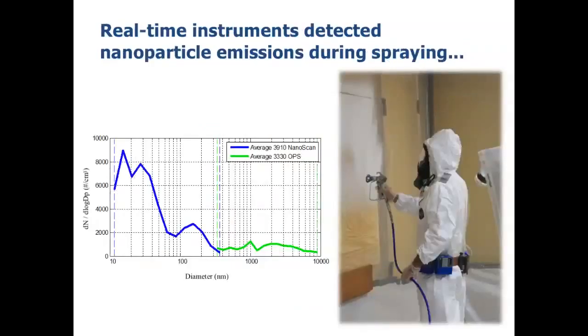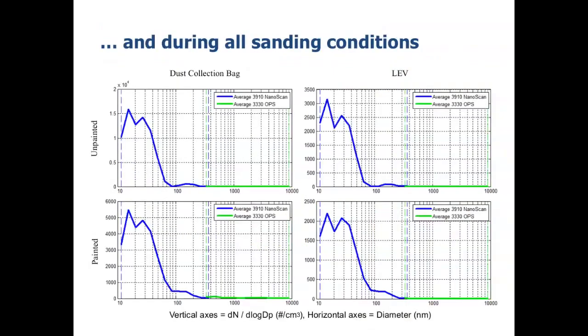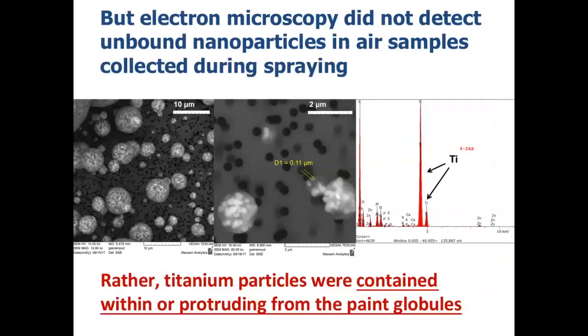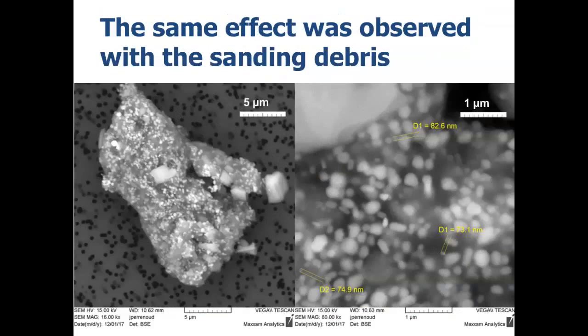And during the spraying, the real-time instruments detected nanoparticle emissions. The same was true during all sanding conditions, as you can see from the blue lines below the 100 nanometer cutoff. However, the electron microscopy did not detect unbound nanoparticles in the air samples we collected during spraying. So rather, what we observed, and as you see on this slide, titanium particles were contained within or protruding from the paint globules. The same effect was observed with the sanding debris, as you can see on this slide.